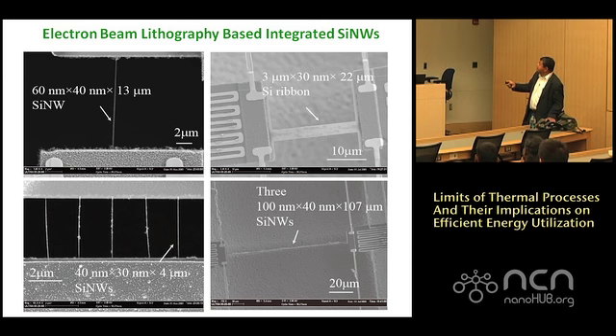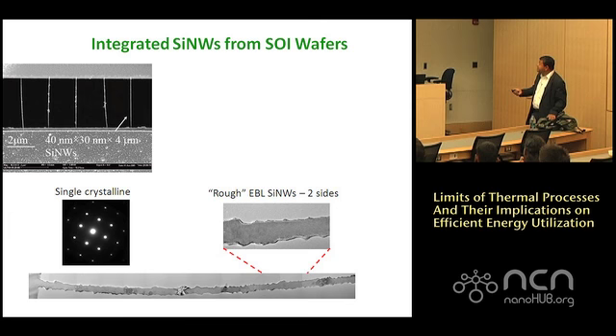So these are now devices. These are 60 nanometers by 40 nanometers. You don't see them very well out here. You can make ribbons, of course. You can make 100 nanometers by 40 nanometers, but long. You can control the length because everything is lithography now. There is no nanowire being put in. These are the devices that we are now trying. This fabrication turned out to be really hard for a variety of reasons. We are now getting the devices and trying them out. These are single crystal. These are roughened. The roughness is not controlled, but nevertheless there's roughness.